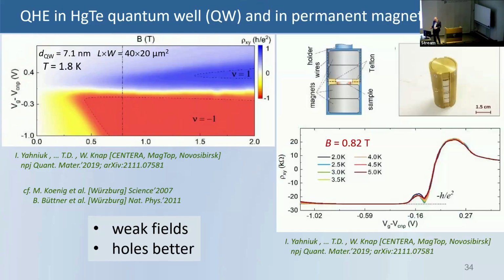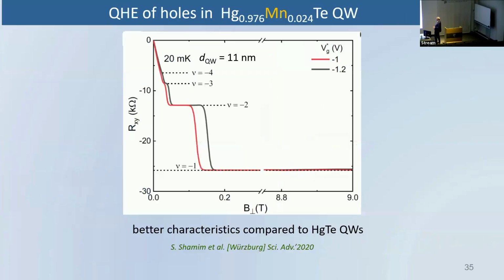And you can actually put this sample in a neodymium magnet. You do not need a superconducting magnet. And if you change electron density at constant magnetic field given by this neodymium permanent magnet, you see a beautiful plateau, which is in a very weak magnetic field in this material. But we said that an even better situation should occur if you add manganese. In the three-dimensional case, it was very clear, and it's also clear in the 2D case.